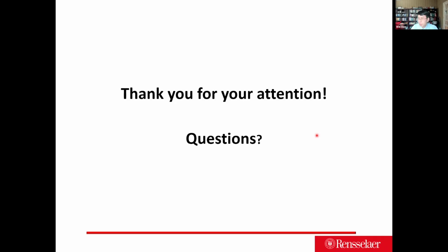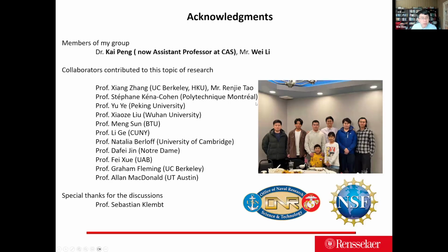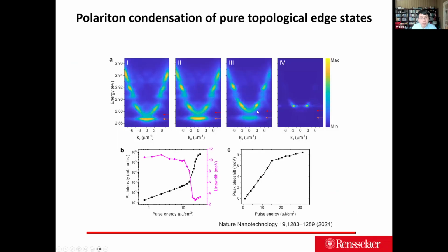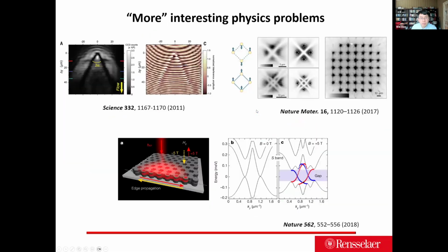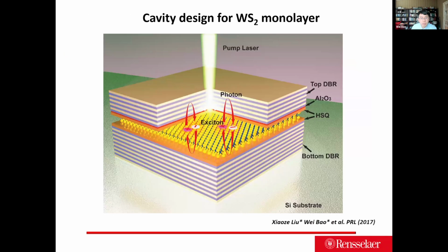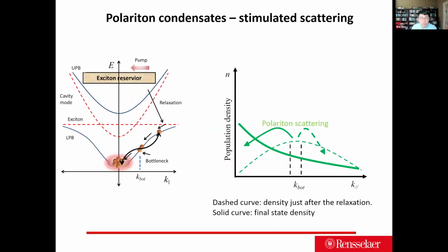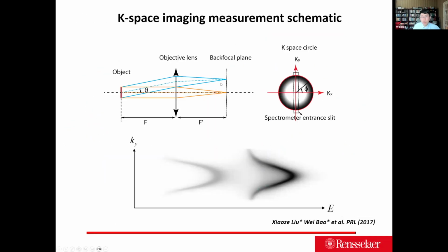Regarding the setup, it is relatively easy, for example, a confocal microscope. Originally, during the birth of the polariton, people used angle-resolved photoluminescence, which is a relatively complicated setup. But later on, once you have a two-dimensional spectrometer, I think in my previous slide I do have one of these, you can just do the back focal imaging.